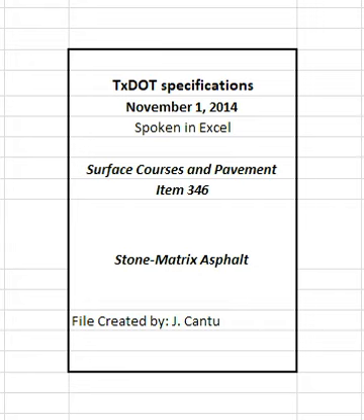4.9.3.3.3 Longitudinal joint density. 4.9.3.3.3.1 Informational tests. Perform joint density evaluations while establishing the rolling pattern, and verify that the joint density is no more than 3.0 pcf below the density taken at or near the center of the mat. Adjust the rolling pattern, if needed, to achieve the desired joint density. Perform additional joint density evaluations at least once per sublot unless otherwise directed.